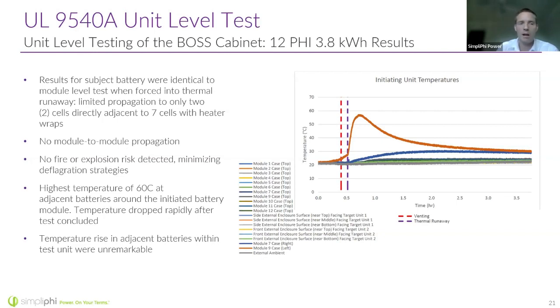Not only that, but the highest temperature of the adjacent batteries, outside of the battery that was forced to go through an off-gassing event, was only 60 degrees Celsius. And after we concluded the test and turned the heaters off, the temperature rapidly dropped. So again, this is really showing you that there's some safety here. This is not a certification, just a test, but it's showing you that it was really kind of an unremarkable